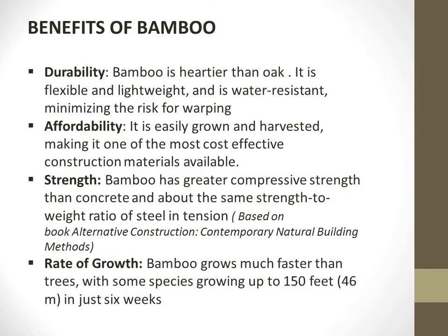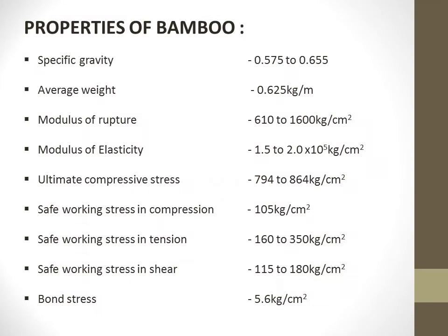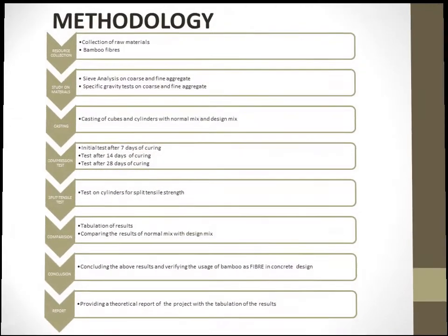These are the benefits of bamboo: durability, affordability, strength, and rate of growth. These are the properties of bamboo. Specific gravity was found to be 0.575 to 0.655, and the modulus of elasticity was found to be 1.5 × 10^5 kg per cm² to 2 × 10^5 kg per cm². The bond stress was found to be 5.6 kg per cm².